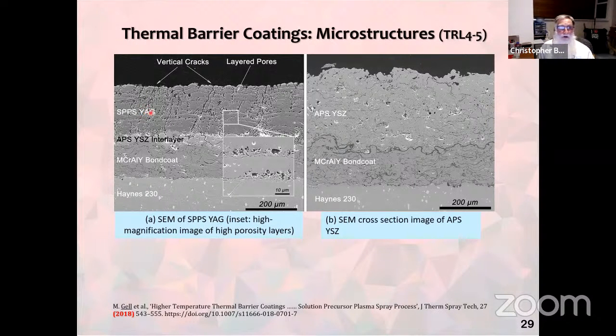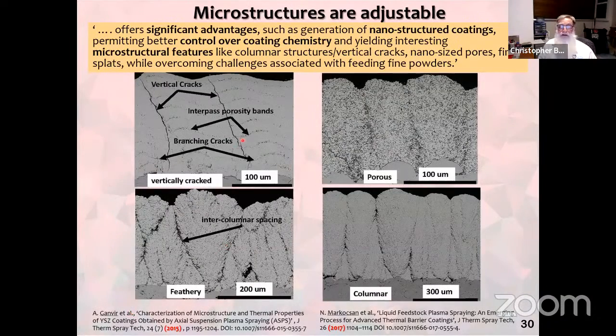with microstructural features of vertical cracks and layered pores. The vertical cracks mimic the columnar structure of a PVD coating. But this has been produced under atmospheric conditions. And the layered porosity is occurring in bands and has been proven to be a very effective impedance to thermal conduction. So it makes a good thermal barrier coating, for example. And Maury Gell at Storrs in University of Connecticut has published in this area relatively recently. And others have also done this.